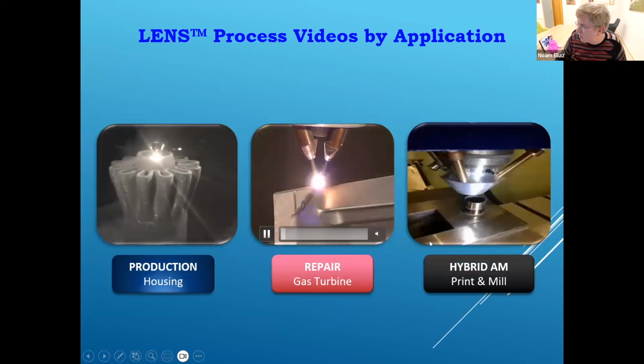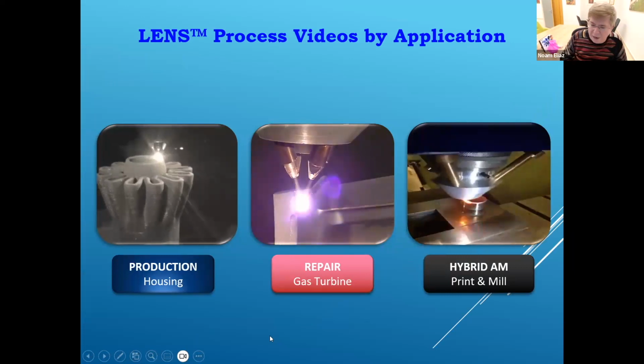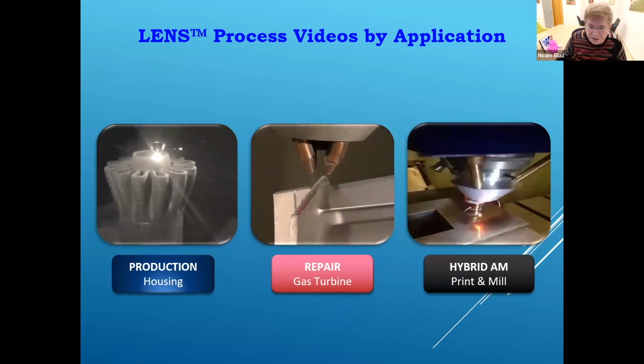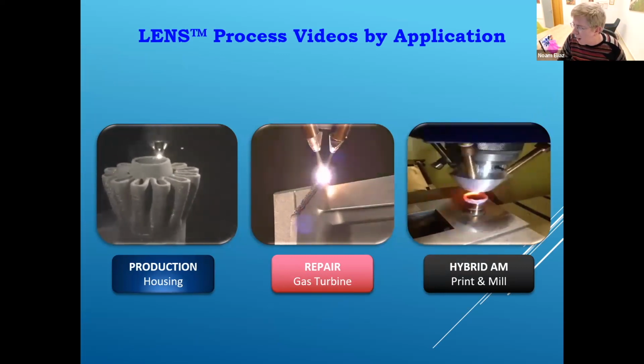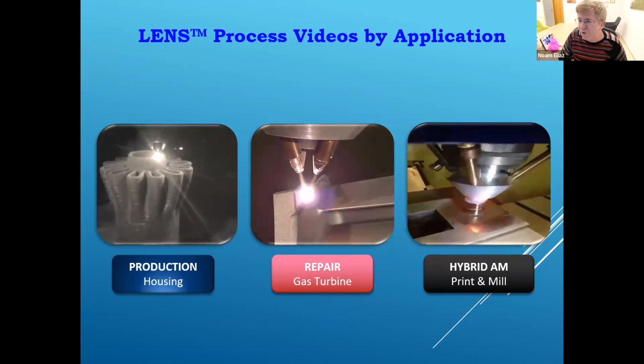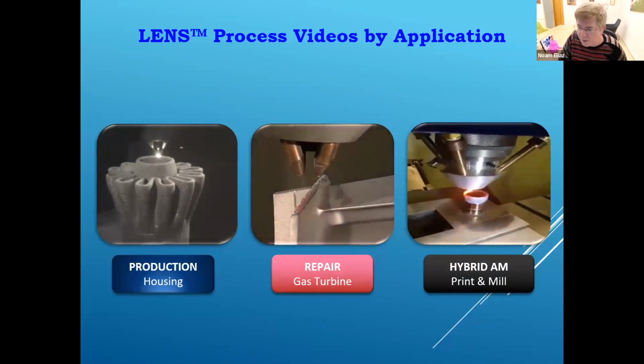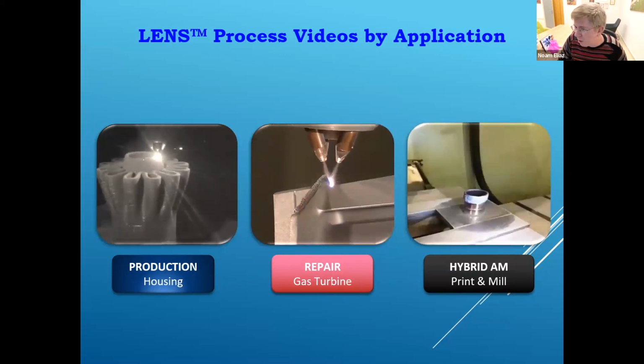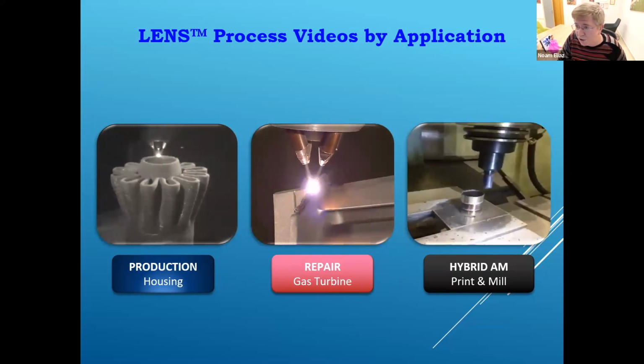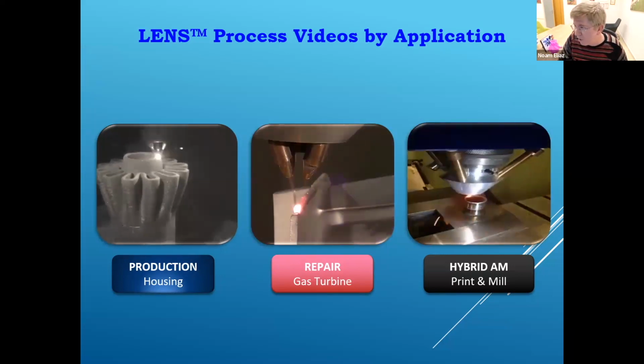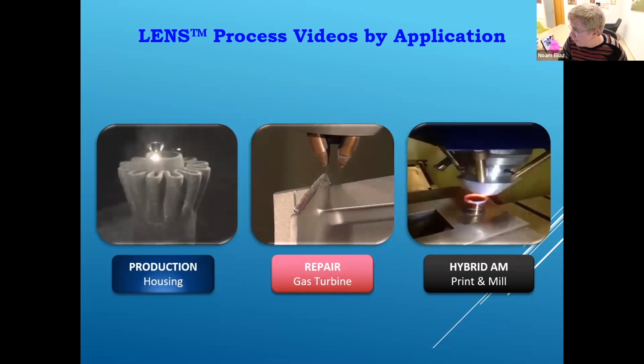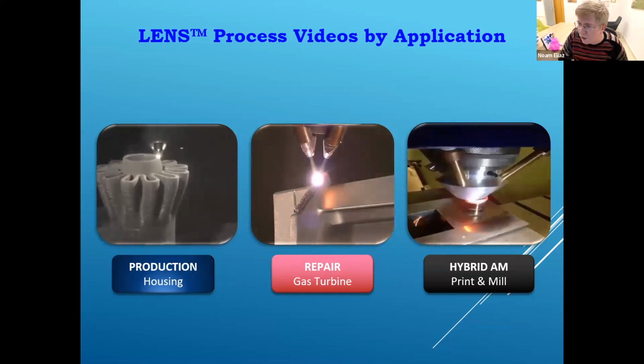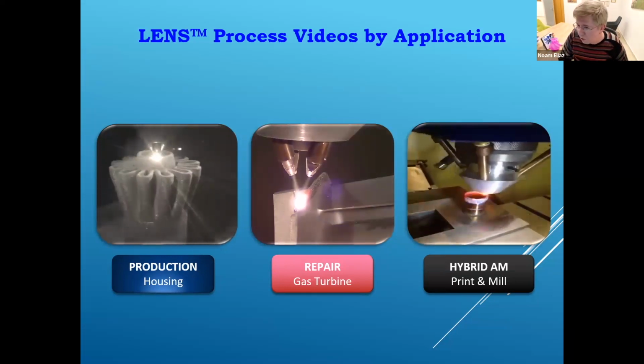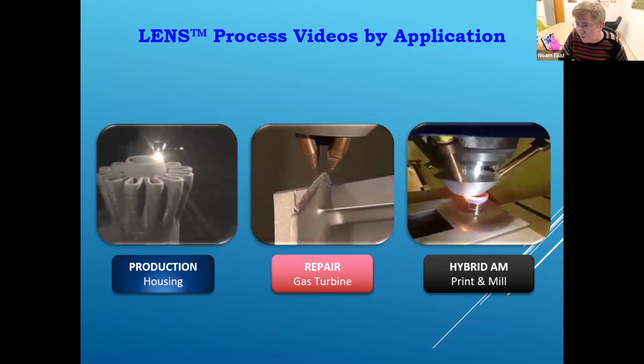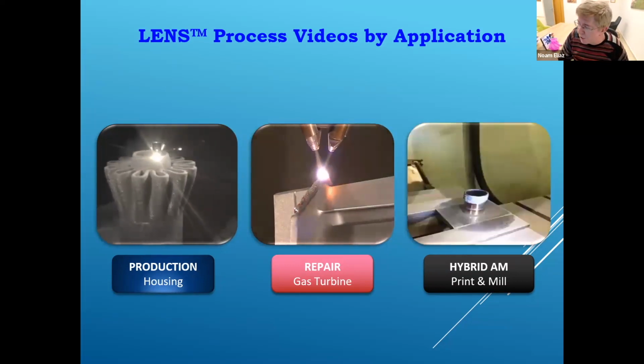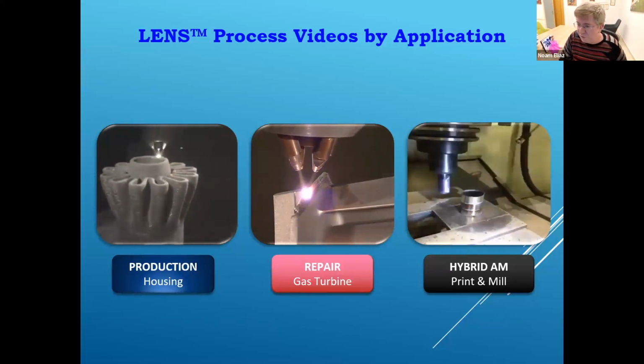So here you can see three examples of the use of directed energy deposition. On the left-hand side, you can see a Bell helicopter exhaust that was fully printed from scratch. In the center, you can see repair of turbine blades. For instance, there are some stages that are routinely repaired using this technology. This reached the highest TRL and MRL levels there. On the right-hand side, you can see hybrid additive manufacturing, like the machine that we have at Tel Aviv University, that has both additive and subtractive capabilities. So it combines both 3D printing, or additive manufacturing, and CNC milling, as you can see here.